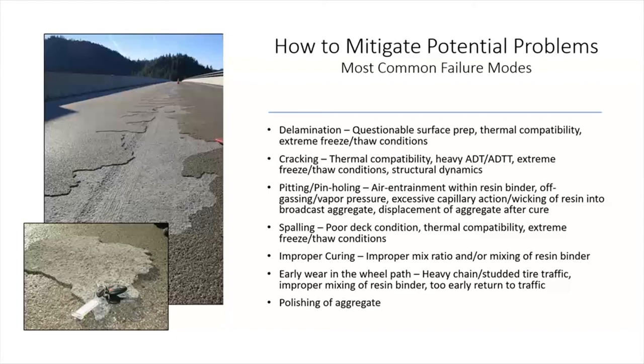Pitting and pinholing are not the same. Sometimes they're considered the same, but if you entrain air in the resin when you mix it, I've seen them take a mixer in a bucket and plunge it down into the resin, pull it up, and it looks like you're making a milkshake or something. Every time you take that mixer out of the resin binder, it whips up a whole bunch of air in it and it turns into a froth. Well, not a good idea. And then you introduce heavy dynamic truck traffic and chains and studded tires and freeze-thaw conditions and long spans, you might get cracking. Pinholing can happen on a hot day.